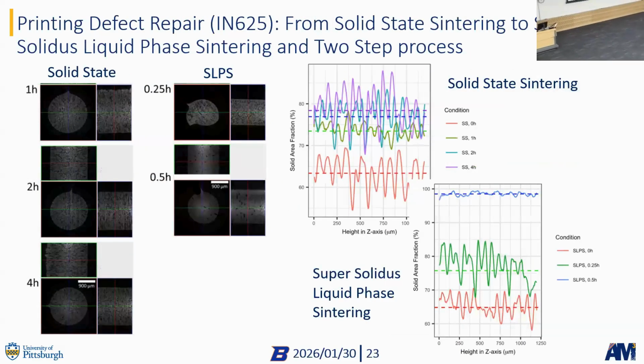So one thing that we did is we looked into using supersolidus liquid phase sintering. So just going a tick into the region where we have a liquid phase forming, okay? And we don't do this very long. We just do this for a brief moment to form this liquid. The liquid is formed on the particles, basically coating the particles and then helping the densification process quite a bit. And by doing so, we can actually reach, so this is the solid state sintering, we can actually reach with supersolidus liquid phase sintering for half an hour, really dense structures, right, in 3D.